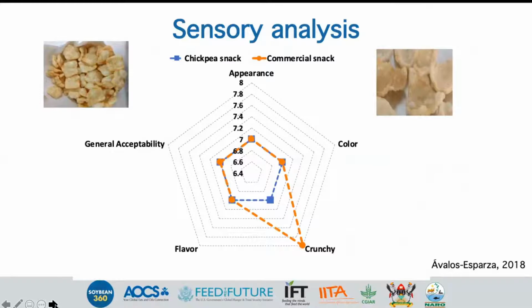Sensory acceptance was compared using a 9-point hedonic scale with an untrained consumer panel of adolescents. It was observed that the chickpea enriched snack reached a value of 7 for appearance, taste, and overall acceptability, and showed no significant difference with the commercial snack. On the other hand, the commercial snack reached a value of 8 for the crunchiness. The difference in crispness is due to different formulas. A snack with a higher protein content will have higher density, however, it was accepted by the consumer.